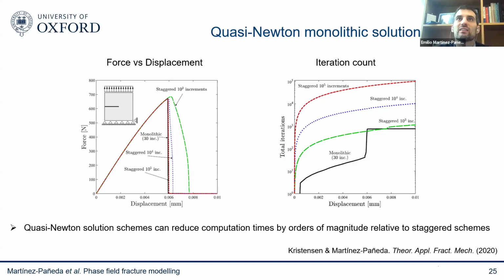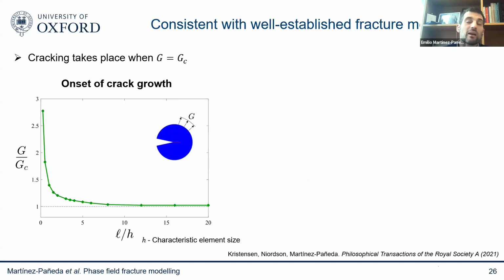Okay, why is it physically sound? Well, because it's based on fracture mechanics and the thermodynamics of fracture, so it predicts failures based on input parameters that we fully know. Basically, the input parameter you need is the fracture toughness, the GC, and you can show it mathematically using gamma convergence, but you can also show computationally that indeed this is the case. You predict the fracture would initiate when your energy release rate reaches a critical value, or your stress intensity factor reaches the fracture toughness, a critical value.